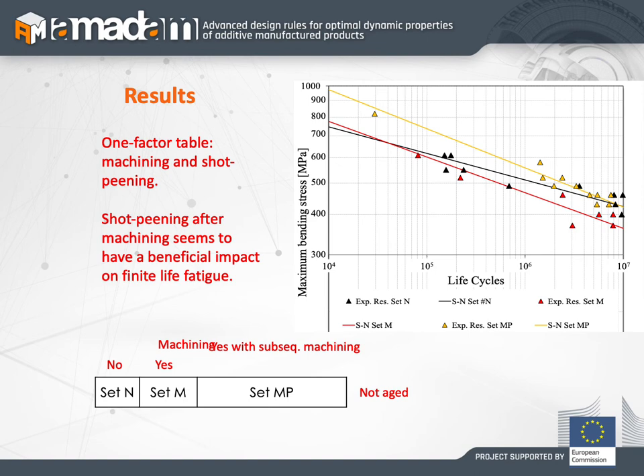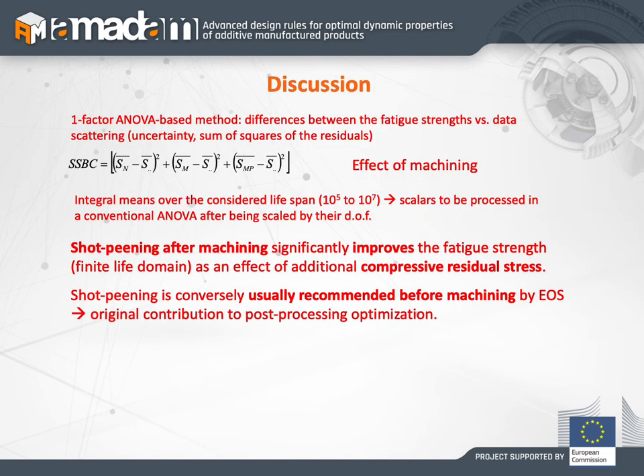So although there is an increase in the roughness if we perform the shot-peening after the machining, we have an increase of the fatigue limit and of the fatigue resistance. Obviously, all the considerations we have made before have to be confirmed by the mathematics, and therefore we have analyzed the results data by applying the analysis of variance. And the significance of the combination of aging and machining effect has been confirmed, as well as that it is better to perform the shot-peening after the machining operation.